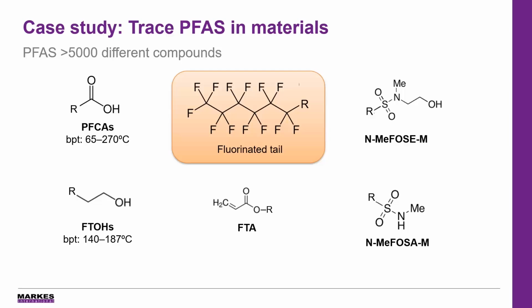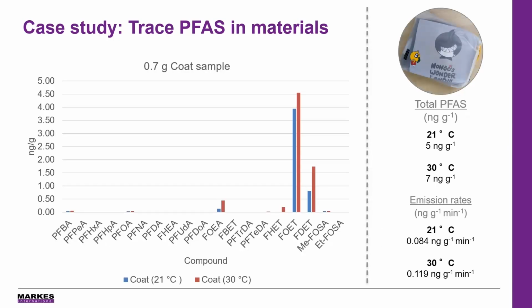So in this case study, we are looking at new coat smell, I guess is the best way to describe it. We looked at some waterproof clothing for children that we bought online, and wanted to see whether or not something that we bought straight off the internet would have these kind of compounds, and it does. Immediately what we did was take 0.7 grams of coat and we placed it into the microchamber, and we tested it at both 21 degrees and at 30 degrees.